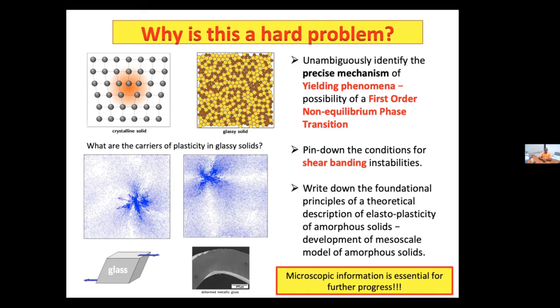Okay, so let me quickly tell you why these problems are so difficult to understand. In crystals, defects are very easy to characterize, and when you deform them, plasticity in crystals can be understood mostly via how defects move under applied shear. But when you look at a disordered solid, even defining a defect is a huge problem. So the question is, what is the carrier of plasticity in glassy solids? With recent understanding, mostly from microscopic simulations, there are these local plastic events, which look like a quadrupole kind of structure. And it came thanks to Eshelby's solutions, which match exactly with this kind of defect. So this is believed to be the soft zones, or the equivalent of defects in disordered solids, and they may be the primary carriers of plasticity in glasses or amorphous solids.